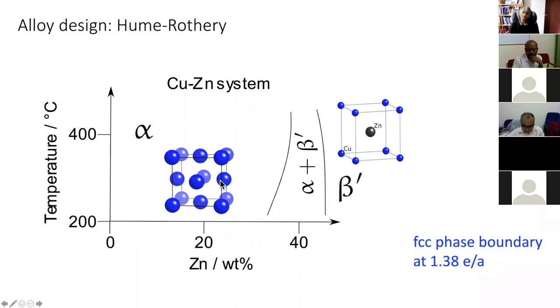So this is the copper-zinc system where we have this alpha brass, which is FCC, and beta prime, which is primitive cubic. At a higher temperature, the beta prime is disordered, and therefore it becomes body-centered cubic. But this is what we call primitive cubic, because this site in the center of the cube is not equivalent to the site at the corner. So there's actually a pair of atoms that you place at each lattice point of a primitive cube corner. So you can't call this body-centered cubic. It's actually a primitive cubic lattice.